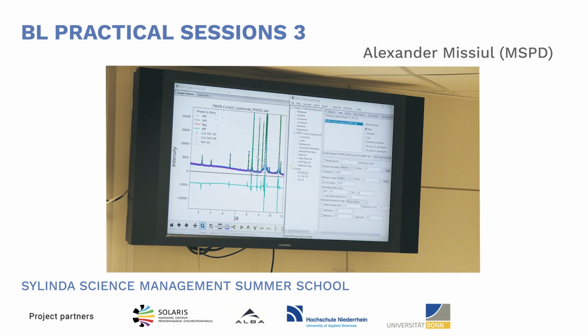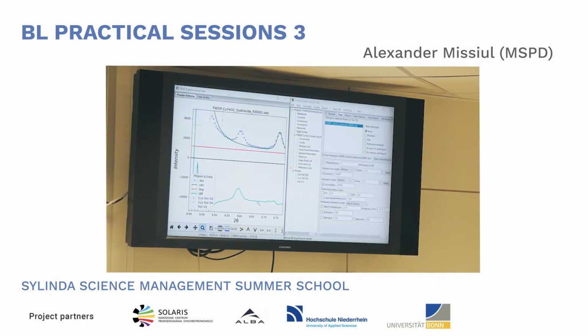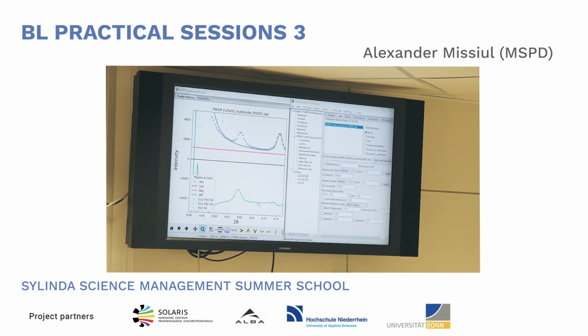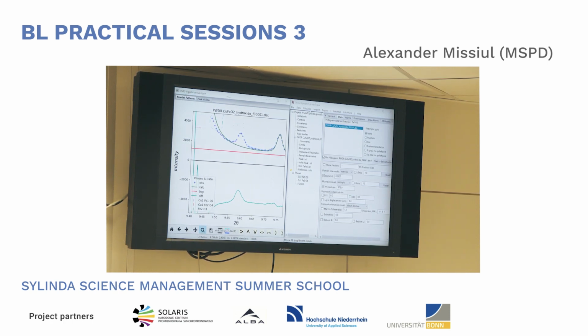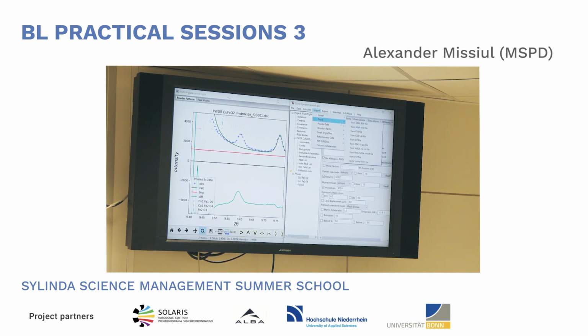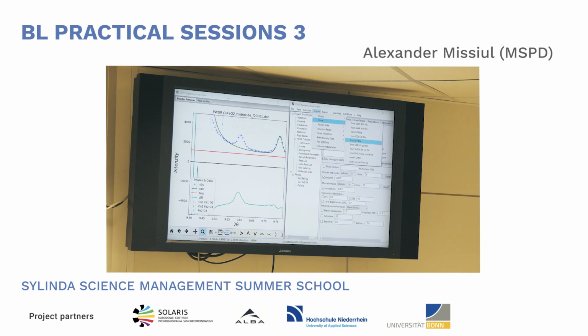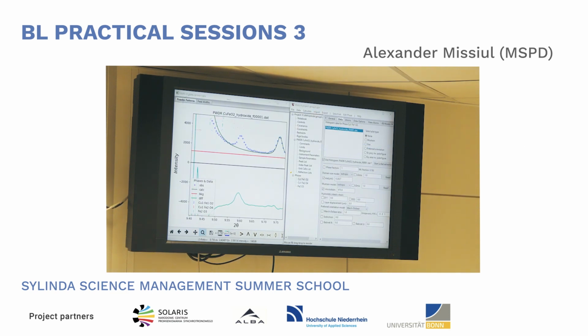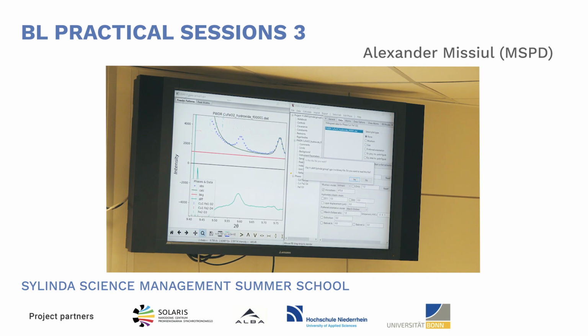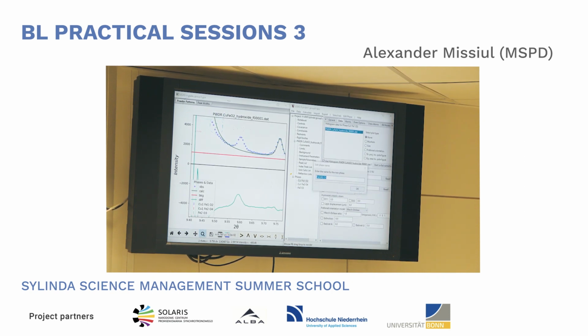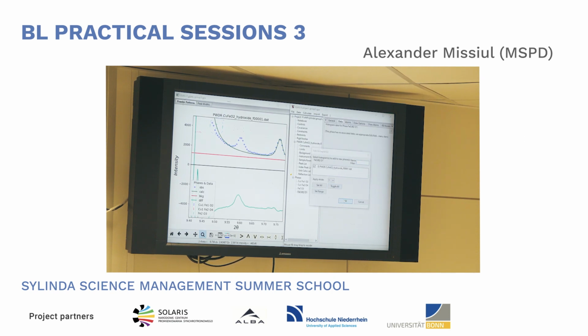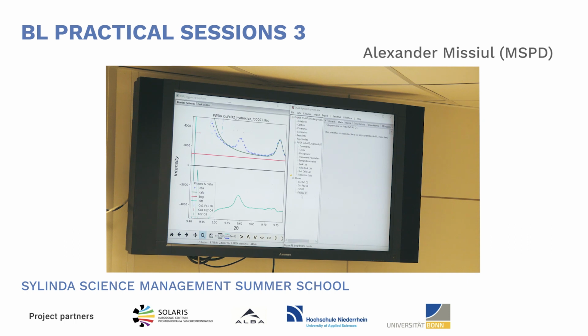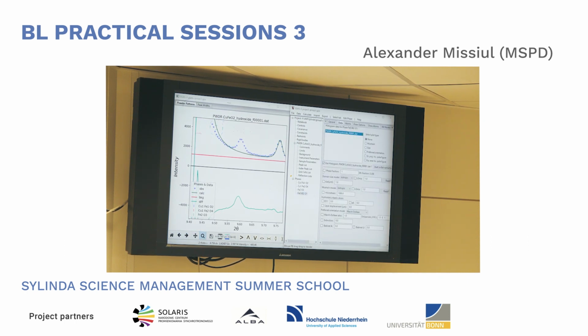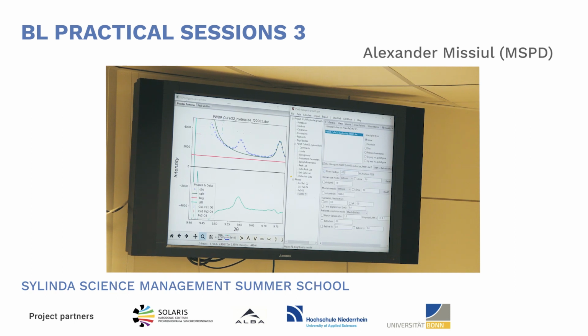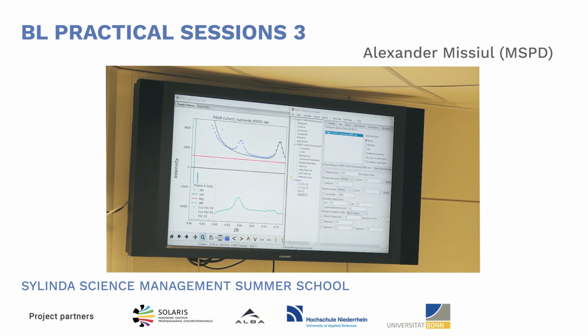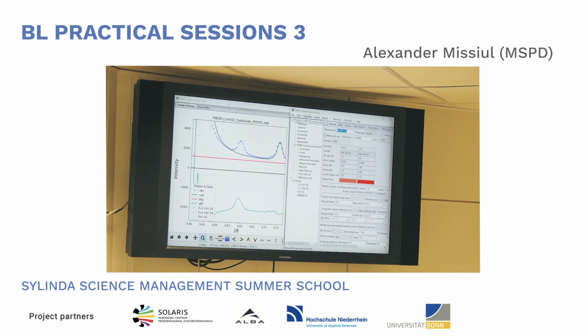But you see now immediately that, in fact, we have more impurity peaks that we did not find with the database search. Just because I know what it is, I will add it. It is also iron oxide, but it is iron plus 2. I will take it from here. This one, just because the database one required a bit more refinement. I don't want to spend much time on this. So let's start. Okay, and also it did not refine very well, so I will not do a real refinement of this one.